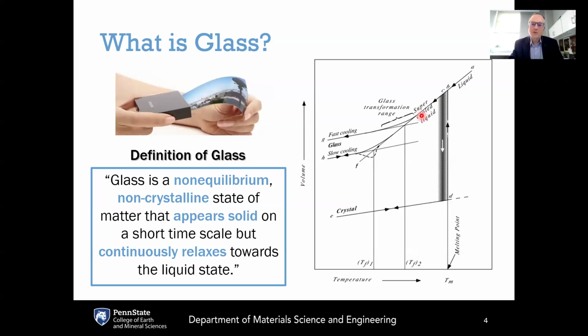Now, at some point, the supercooled liquid becomes cooled to a low enough temperature where the kinetics that are associated with that viscous flow process become slow compared to the time scale on which you are observing them. So, for example, if you are looking at a supercooled liquid in the lab and pouring it out of a crucible, as the temperature is lowered, that viscosity is becoming orders and orders of magnitude higher. When that happens, the kinetics of the atoms are becoming slower and gradually they appear to freeze in, at least on our time scale of observation, whether that's minutes or hours or days or years. On a laboratory time scale or a human time scale, they are essentially frozen.